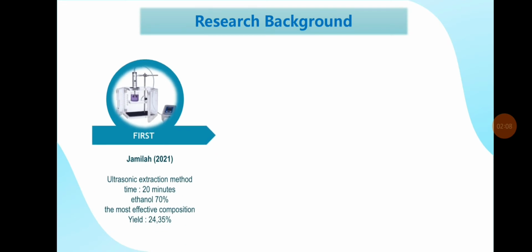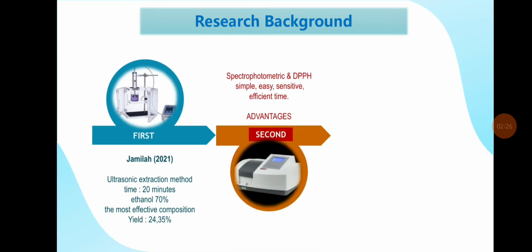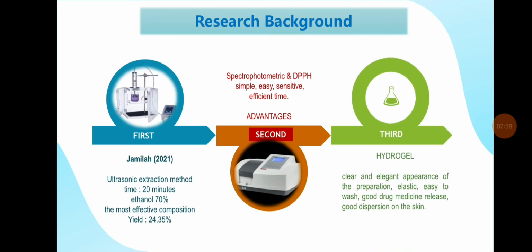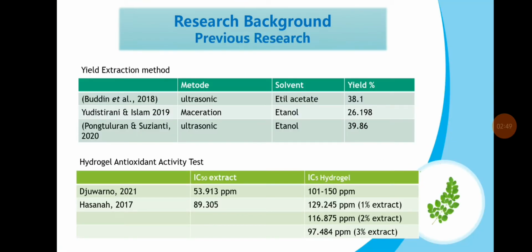Based on the research of Jamilah 2021, the ultrasonic extraction method of Moringa oleifera leaves with 20 minutes using ethanol 70% solvent is the most effective composition, with the yield of 24.35%. Then, the spectrophotometric method using DPPH is simple, easy, sensitive, and time-effective. The advantages of gel preparations are a clear, elegant appearance, elastic, easy to wash with water, good medicine release, and good dispersion on the skin. My previous research about extraction methods from several journals showed that sonication extraction with ethanol solvent gives the best result.